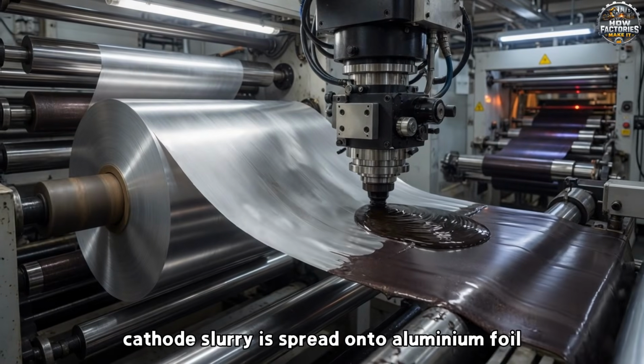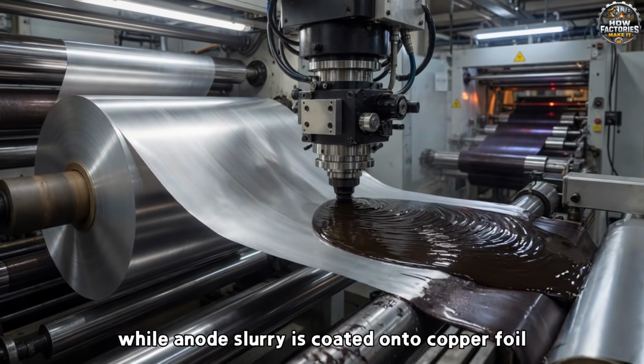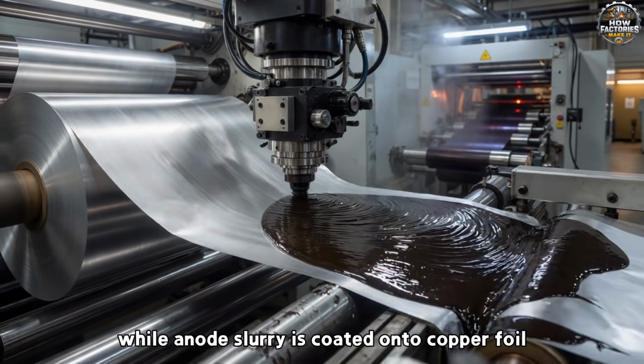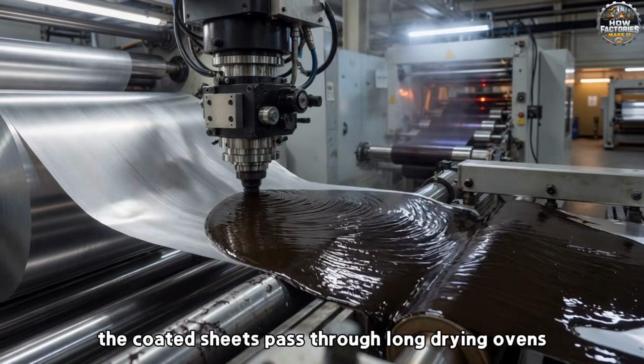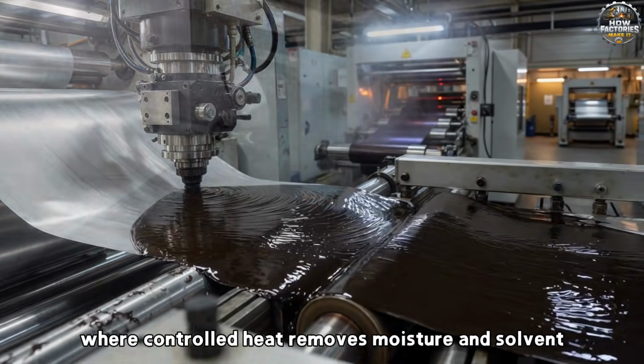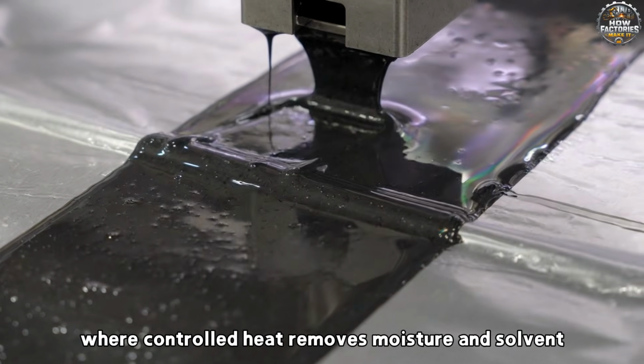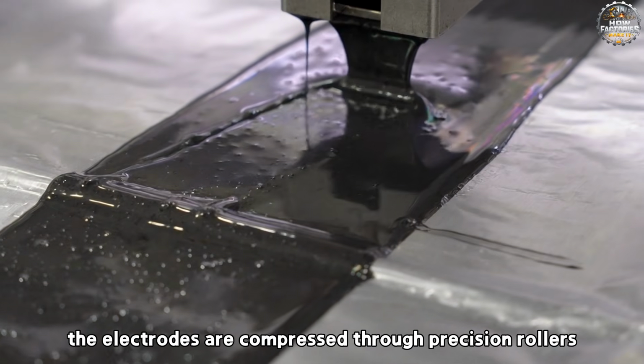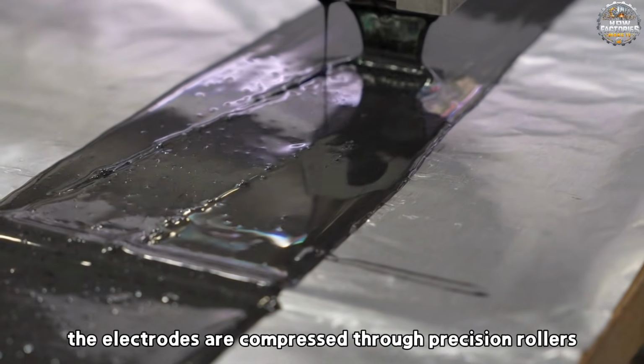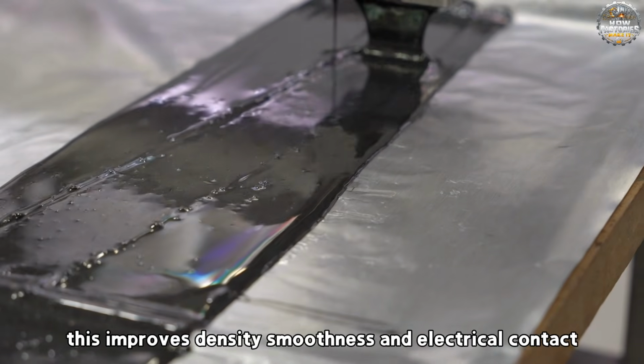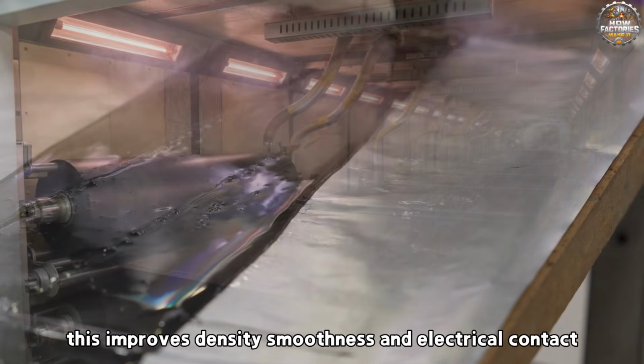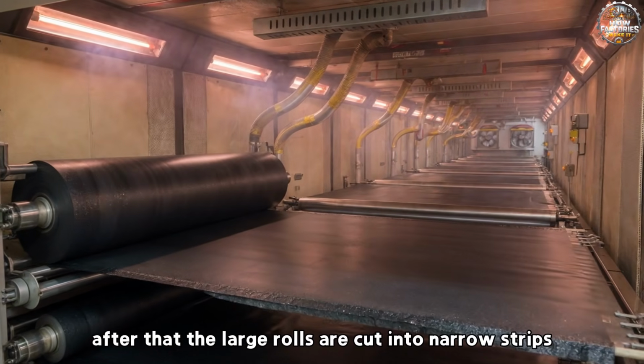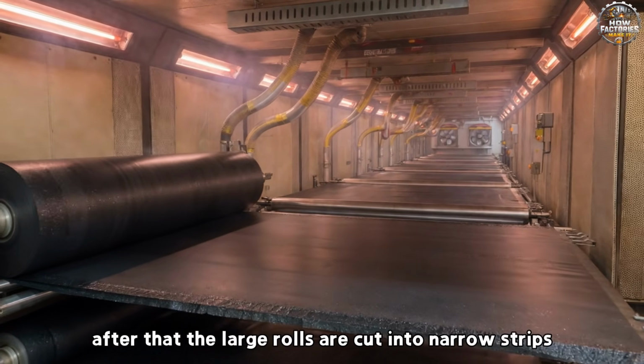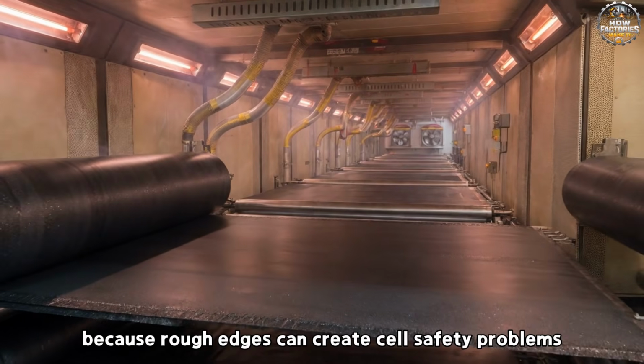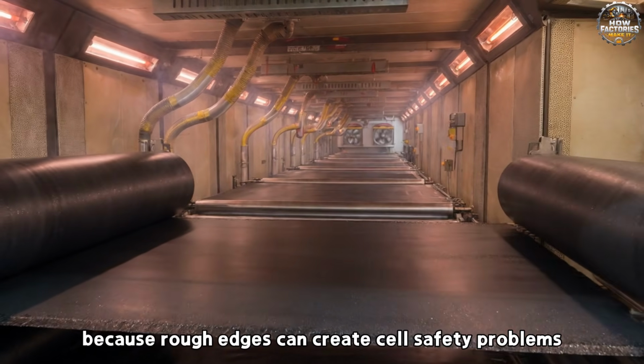Cathode slurry is spread onto aluminium foil, while anode slurry is coated onto copper foil. The coated sheets pass through long drying ovens, where controlled heat removes moisture and solvent. The electrodes are compressed through precision rollers. This improves density, smoothness, and electrical contact. After that, the large rolls are cut into narrow strips. The edges must be clean because rough edges can create cell safety problems.